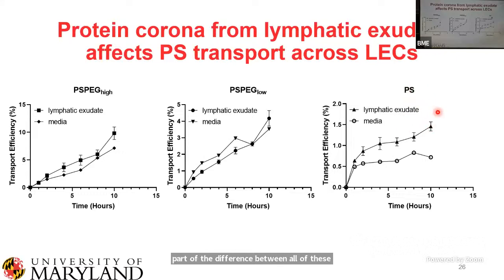when we pre-incubated those in the lymphatic exudate, you do actually see an increase in transport of these particles. So maybe even if you're working with formulations that are not pegylated, if you get the right protein pre-incubation, you could enhance the transport of these particles into lymphatic vessels.